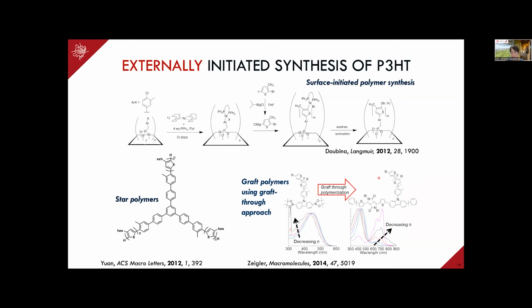Previously, people hadn't been able to do surface-initiated polymerization. By having this initiating scheme, we were able to do that. We were also able to make star polymers. We decorated a core with 3 nickel complexes, and we were able to initiate a star polymer synthesis that way.